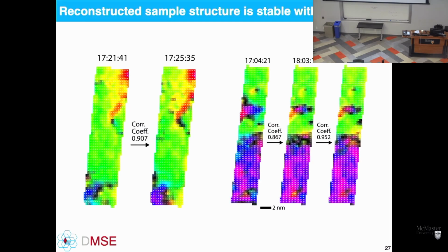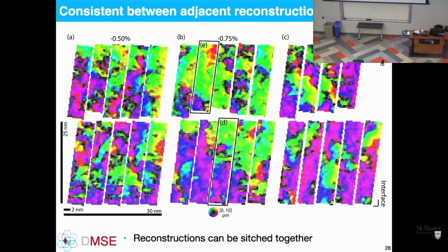These data sets were acquired and reconstructed. You get extremely good agreement through the entire stack. The same thing with ones that are acquired over a much longer period, from an hour to a few minutes. We get essentially the same structural reconstruction from the same region. The polarization is really what the sample is doing. It's not something that comes out of the mathematics.